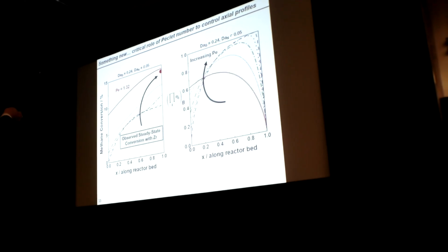So the rates that we developed here, I'm just going back a couple of slides to show you. Yes, so we include the Damköhler number for benzene and naphthalene. We're considering the Damköhler number as kinetics to linear velocity. We are considering the kinetics of naphthalene as well. The rates that I'm showing you are the cumulative rate of aromatics formed, including naphthalene.